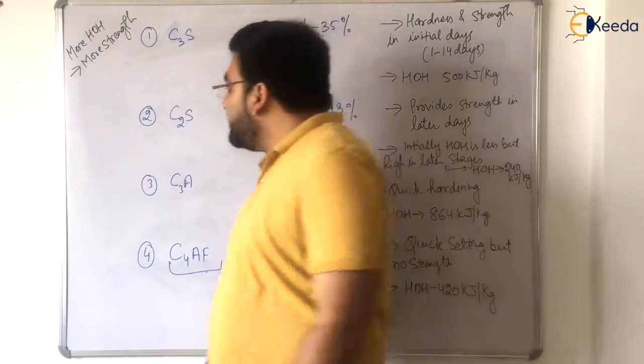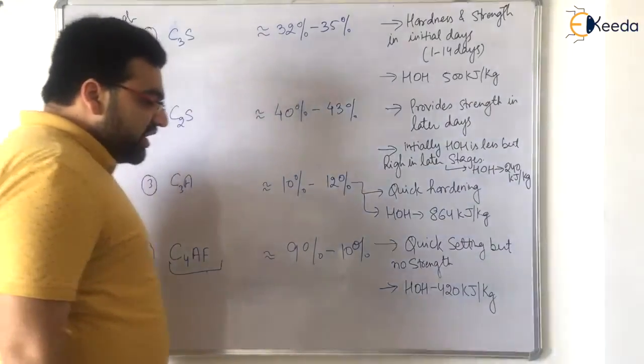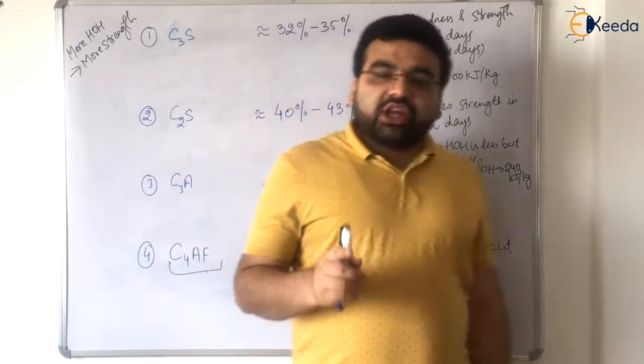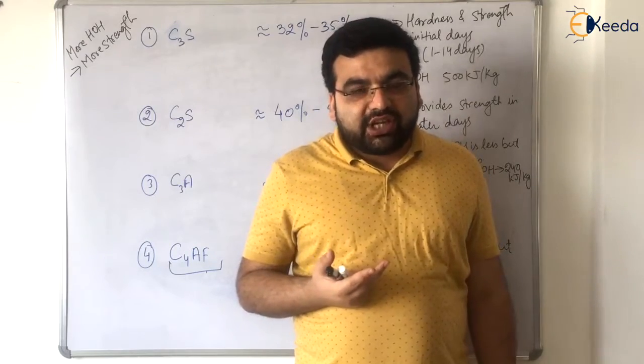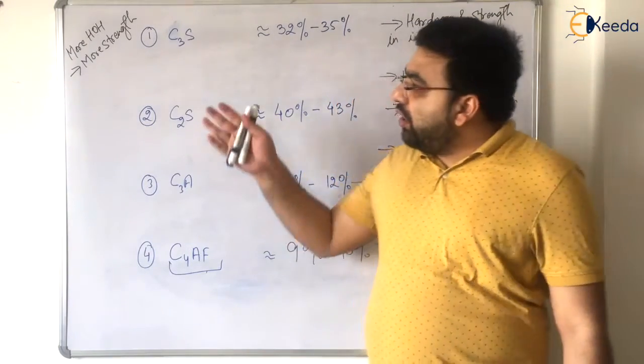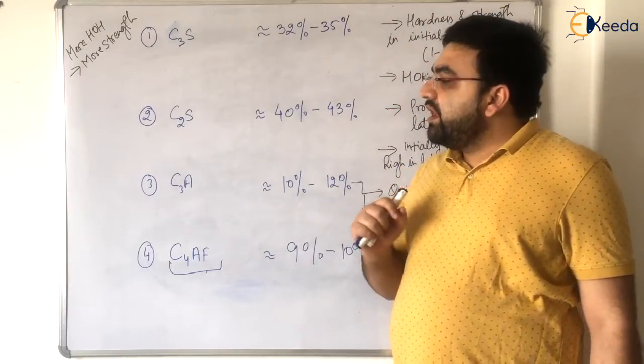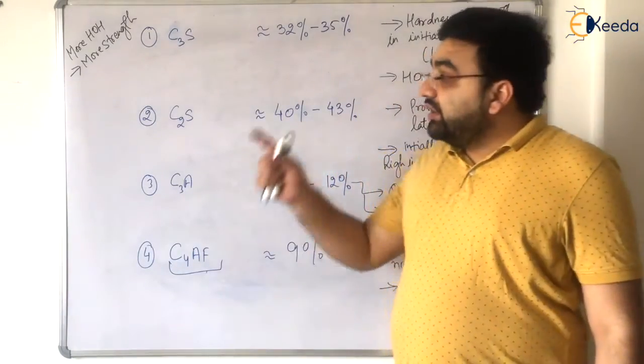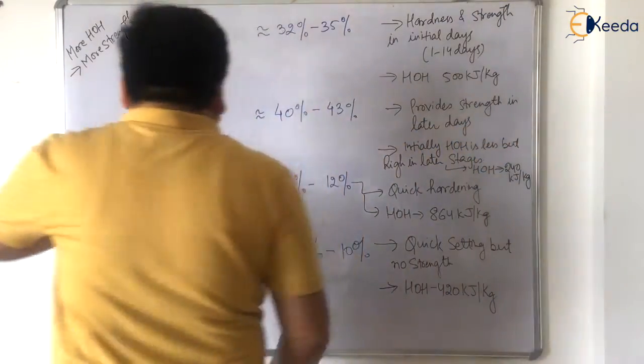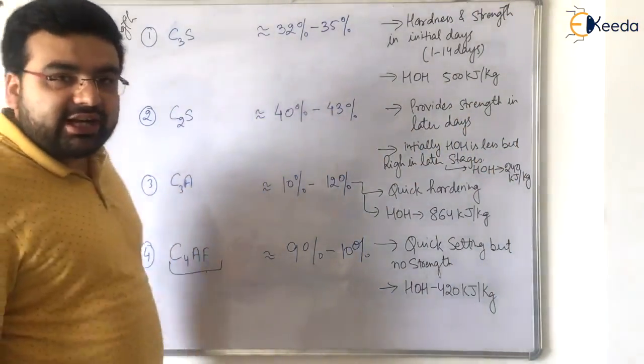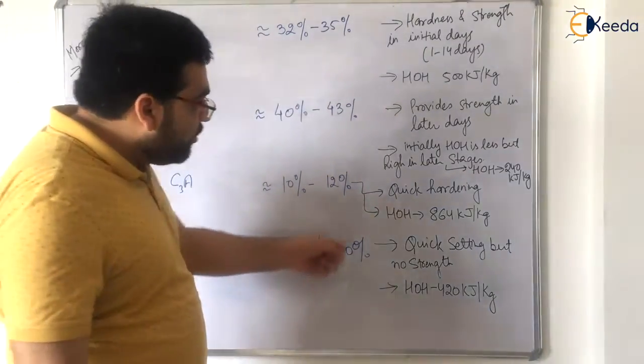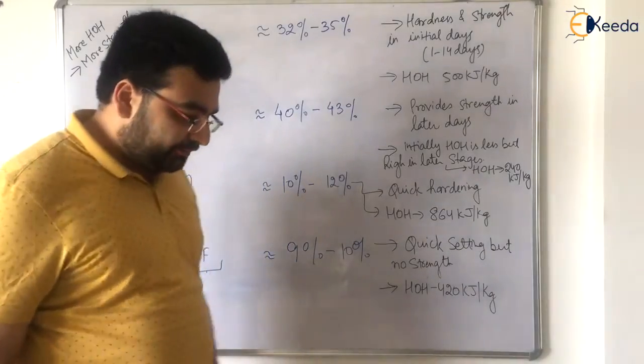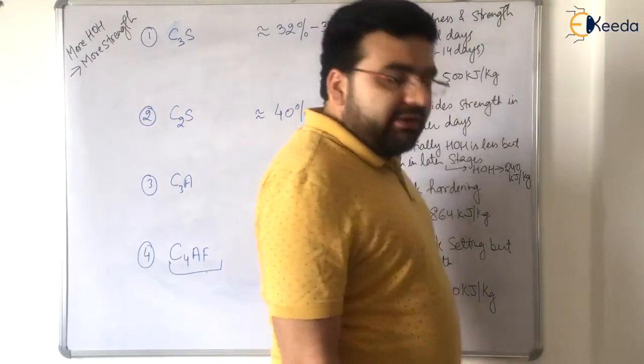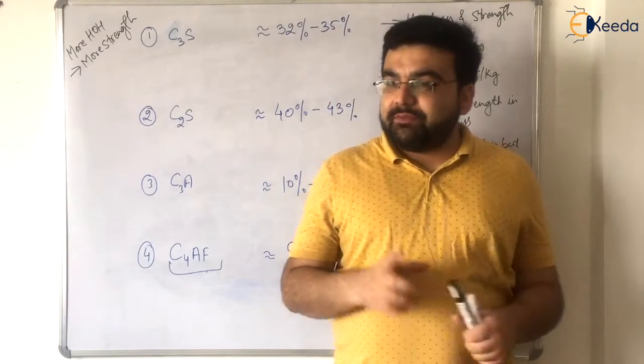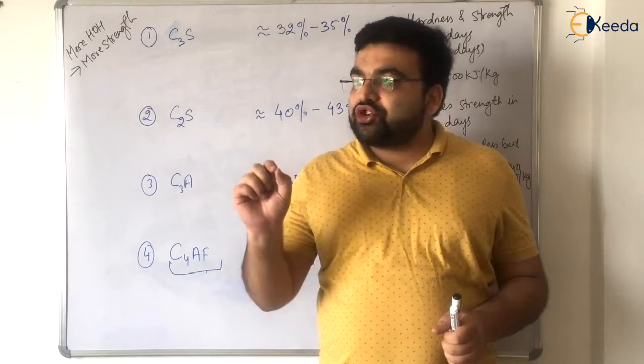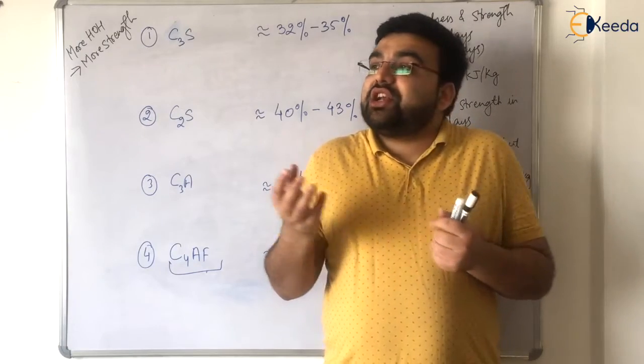Now the second important thing is about the heat of hydration. Just remember one thing. Addition of water in cement is exothermic reaction. Exothermic means heat is evolved, but all these components have different contribution towards the heat, right? The highest heat is evolved by C3A, that is tricalcium aluminate. It is around 864 kilojoules per kg. Now, remember one thing which I am going to tell you that is very important. Heat of hydration is directly proportional to strength. The more heat of hydration, the more strength.